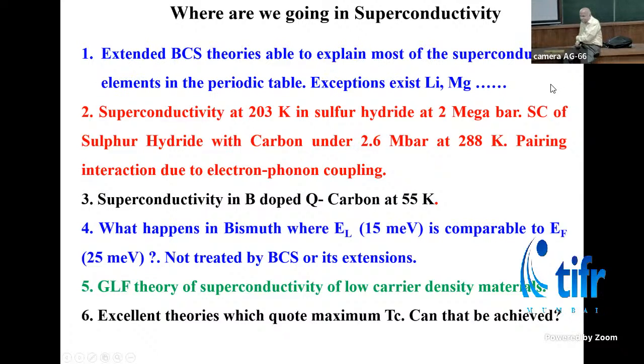Is there something well defined in the optical spectra of very high pressure materials, where you can look at maybe the Raman spectra to look at the electron-phonon coupling? They have done that. Actually, in one of the high pressure studies on the H2S variety, they showed that Raman is the best way to look at the structure, even compared to X-rays. There are a lot of studies on the structure, but it doesn't form a homogeneous compound. Many of them are not forming a single compound, and which single compound is the superconducting one is not being realized from these studies. But work is going on. The idea now is to reduce the pressure and see whether it can raise superconductivity. So some groups are working on that as well.